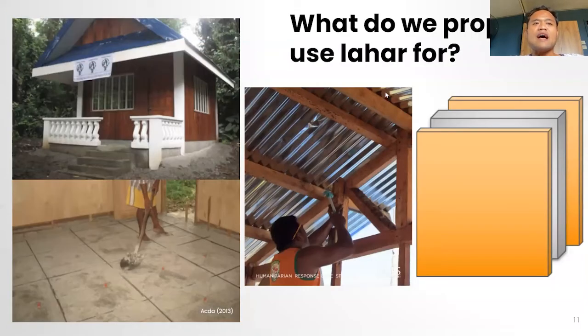So several papers have examined the connections of lahar to agriculture, such that the material has introduced significant chemical benefits for crops, but it is texturally inappropriate for plant growth. The focus of the proposed innovative use is a biological, environmental, and engineering approach. A handful of researchers explored the use of the material for pest control by using it as a foundation, laying down compacted lahar about 5 centimeters thick, composed of the very coarse sand to granule fraction, which is then overlain by the actual concrete.